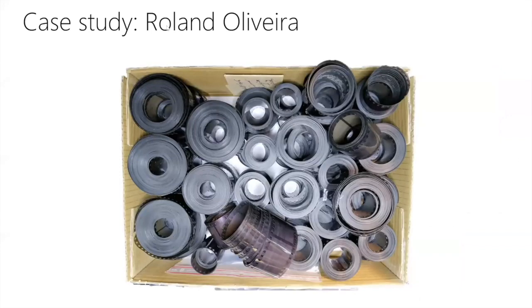This collection comprises a considerable amount of 35mm silver gelatin negatives showing physical deformation. They were rolled and they present stiffness. This set is of the utmost importance to CDI since it contains unique images from the activities of the club in the 70s and 80s. However, the degradation of the films was constraining their access.